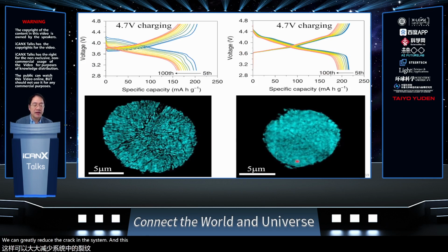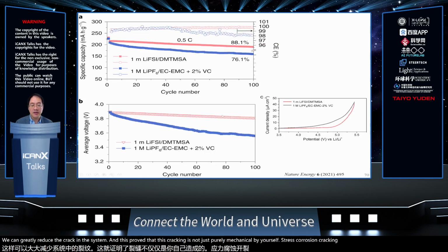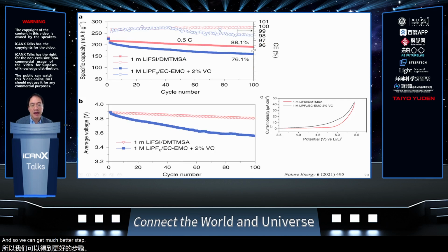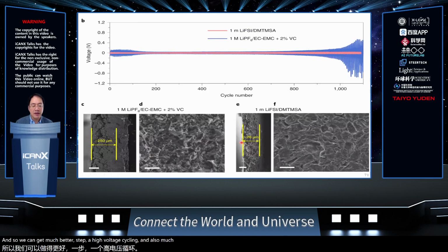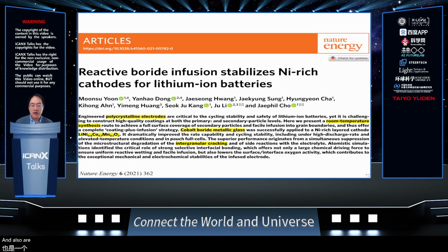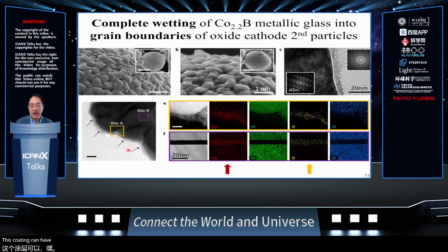And this proved that this cracking is not just purely mechanical, but it's stress corrosion cracking. And so we can get much better high voltage cycling and also much better lithium metal morphology. And also the coating works as well. So in this work, we show that by having a cobalt boride metallic glass coating, this coating can have a 0-degree wetting angle into the grain boundaries. So this cobalt and boron completely wets the grain boundary between the NMC particles.